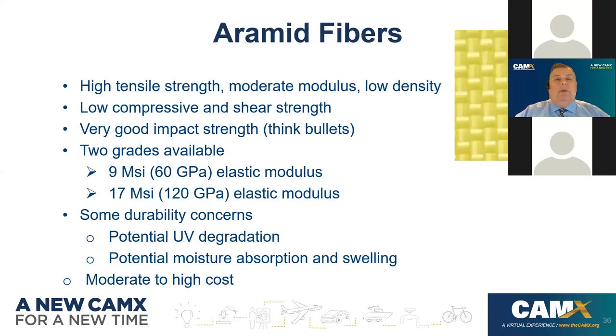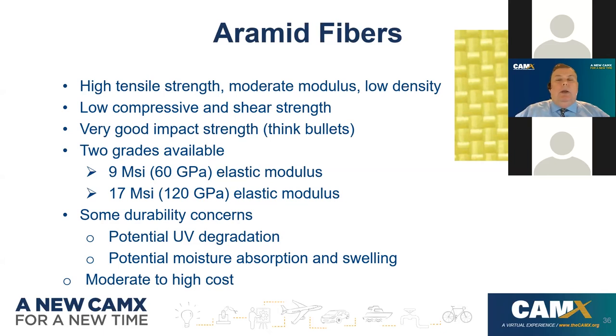Aramid fibers — otherwise known as Kevlar (a trademark name) — have high tensile strength, moderate modulus, and low density. They have low compressive and shear strength but very good impact strength, making them ideal for ballistic armor protecting law enforcement and soldiers. Two types are available with different stiffnesses depending on the application. There are some durability concerns with UV degradation and moisture absorption, so resin selection is very important. Aramid is moderate to high cost compared to glass fibers.